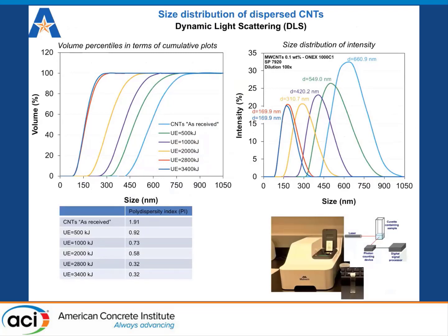In a second step, the particle size distributions of the resulting suspensions can be analyzed with dynamic light scattering tests. In DLS tests, we can measure the z-average hydrodynamic particle diameter, which is obtained from the cumulant analysis of the normalized electric field autocorrelation function. We use the Stokes-Einstein equation with the diffusion coefficient determined from the autocorrelation function.